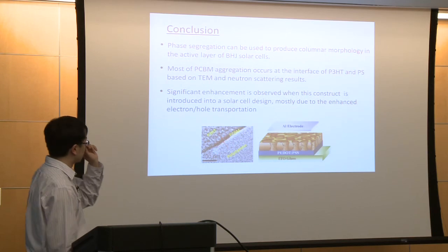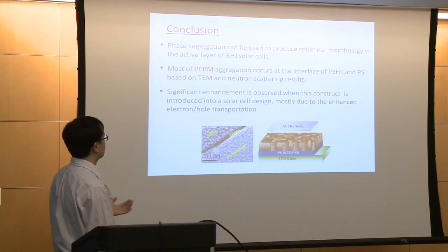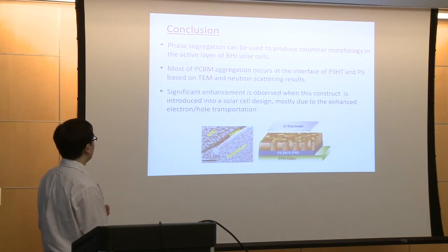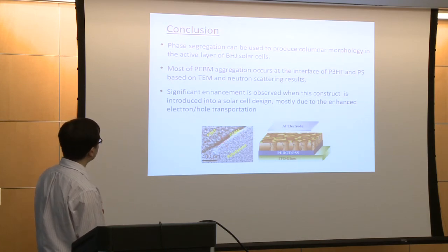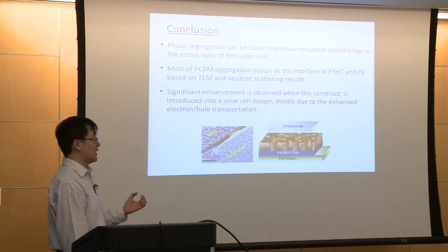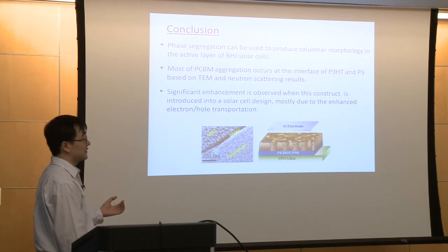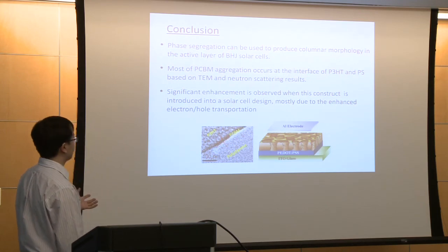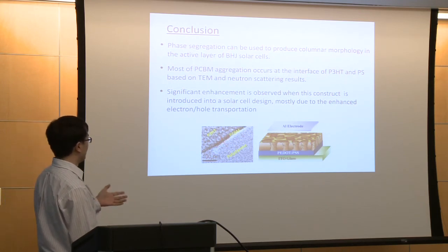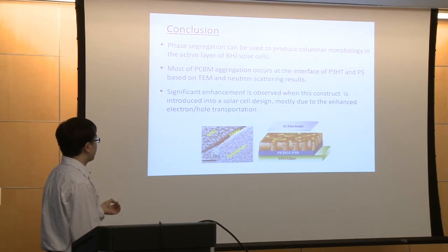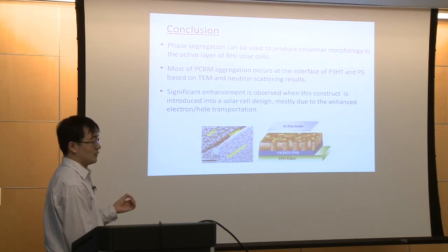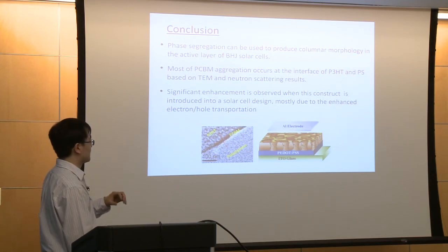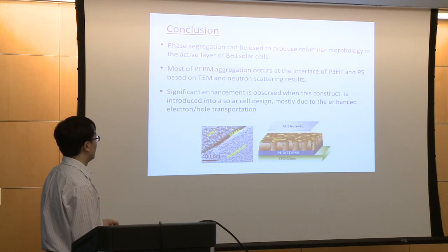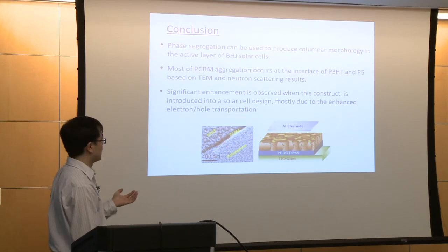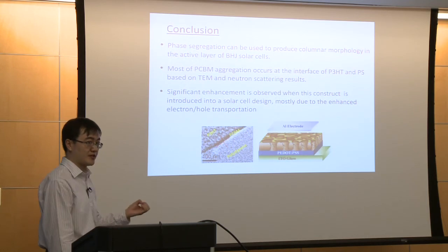So our conclusion is like this. First, we use phase separation to create the columnar structure in the active layer of the BHJ solar cell. Second, most of the PCBM is proven to segregate at the interface between the P3HT and the polystyrene phases. And we confirm that by TEM and neutron scattering. Third, we find a significant enhancement of the power conversion efficiency when we introduce this column structure into the active layer. That's mostly due to the enhanced electron and hole transportation within the active layer.